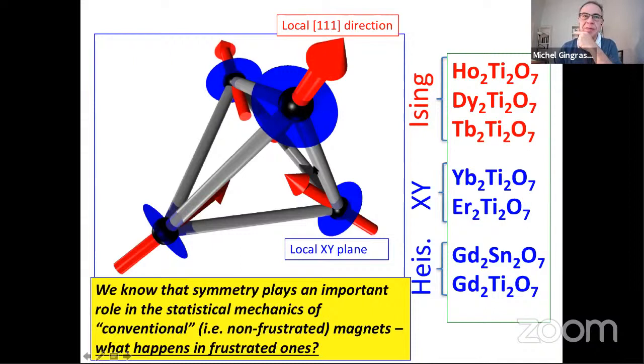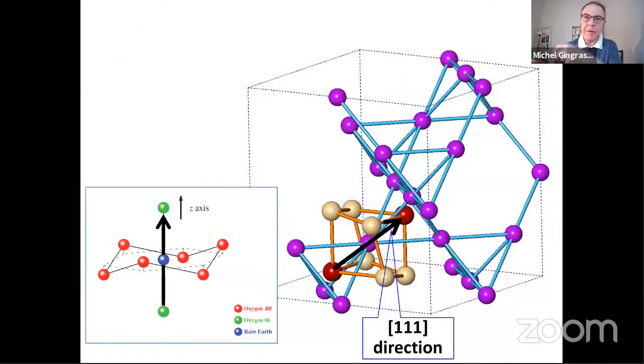So now this is not like the Ising model or the XY model that you are perhaps familiar with, where the anisotropy direction is global, the same for all the sites. The pyrochlore lattice is a non-Bravais lattice, and so each site on the tetrahedra has its own anisotropy.